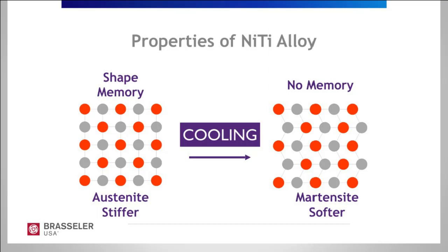And the reason why we've had that shape memory austenite phase is that that stiffer phase is the phase that cuts dentin more efficiently. But actually, every nickel titanium alloy has another phase, which is the martensite phase, which is the softer, malleable phase. And it actually has no shape memory. So if you cool a nickel titanium alloy, what happens is it becomes like a stainless steel file, really. It's soft, you bend it, and it stays where you put it. And it won't come back to that straight original shape. Now that's a property of every nickel titanium alloy. That's good in one way. You can pre-bend, you can get it into a canal very easily. The problem is that at this martensite softer phase, it's a very poor cutter of dentin.